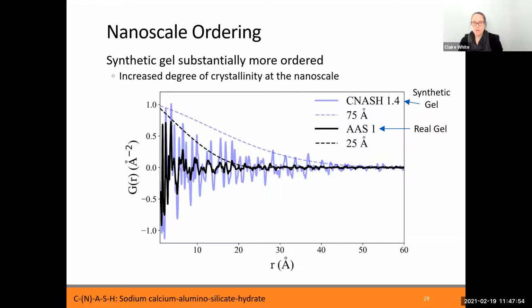And so we can define what's known as a nanocrystallite type size for the gel. And if we look at a CNASH type gel, we end up with a size that's beyond about 60 angstroms. Whereas if we look at the real gel in the alkali-activated slag system, it's a lot smaller in terms of nanocrystallite size. It's 25 angstroms. So this is showing you specifically for these 2 types of gels that the synthetic gel is a lot more ordered. It has an increased degree of crystallinity compared to the gel that we find in the alkali-activated slag system. There's a couple of things that come out of this.